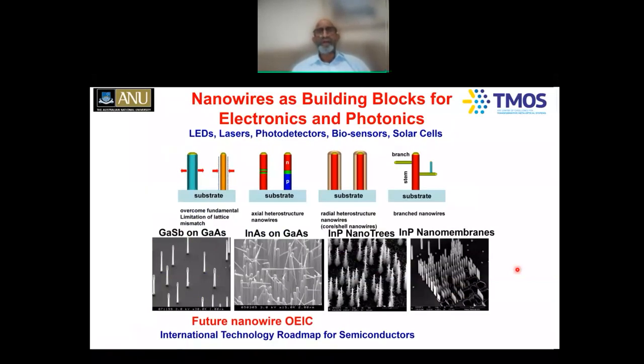Now let me come to the nanowires. Nanowires are seen as the building blocks for electronics and photonics. And what is so unique about the nanowires is that lattice mismatches are no longer an issue. Lattice constant is a unit cell which repeats itself in a crystal. And as and when you have a larger or smaller lattice constant with respect to the substrate lattice constant, these materials either expand or contract without creating any dislocations.